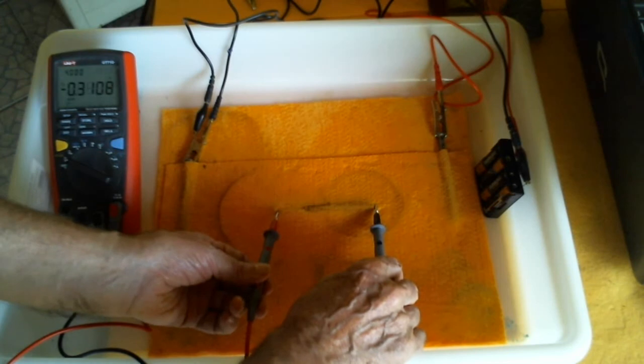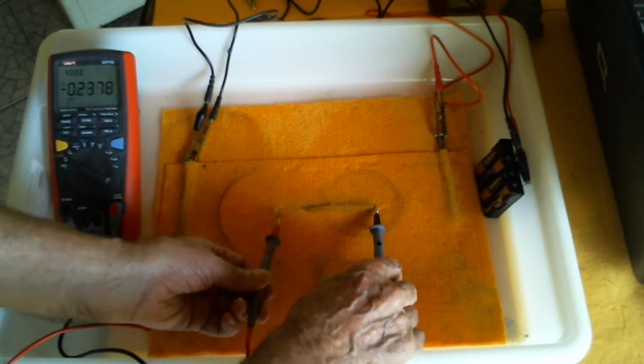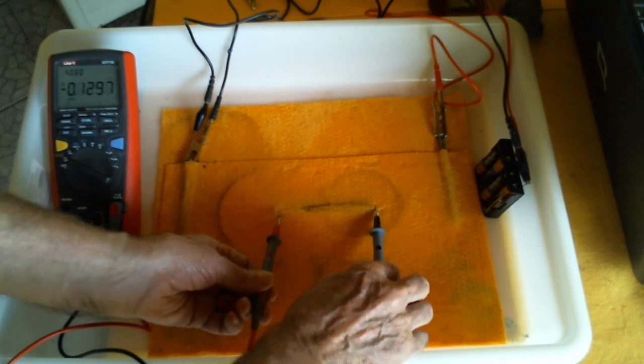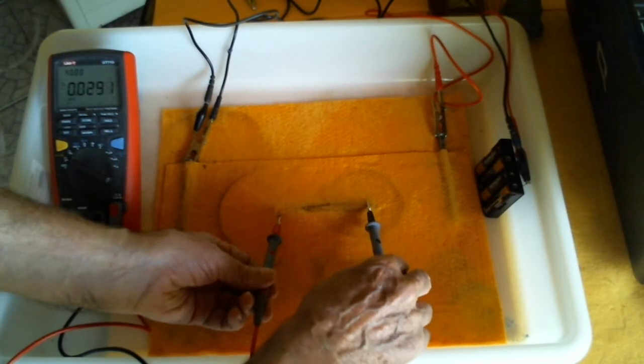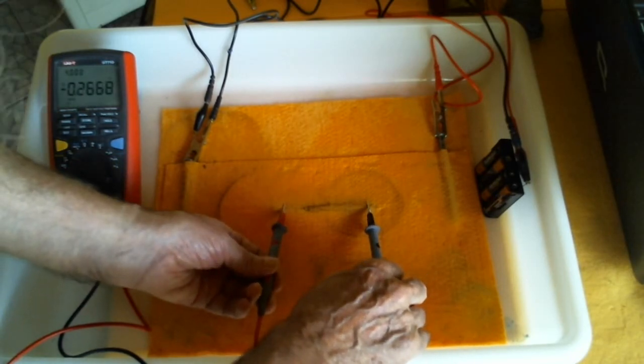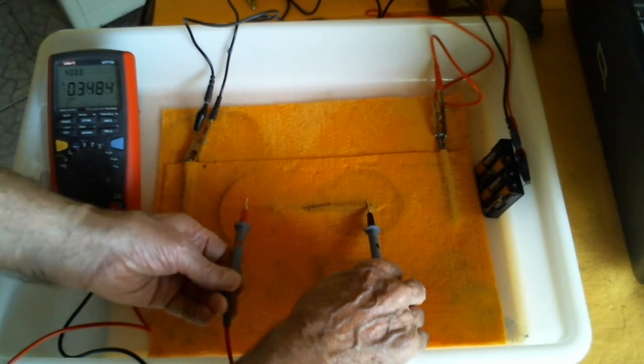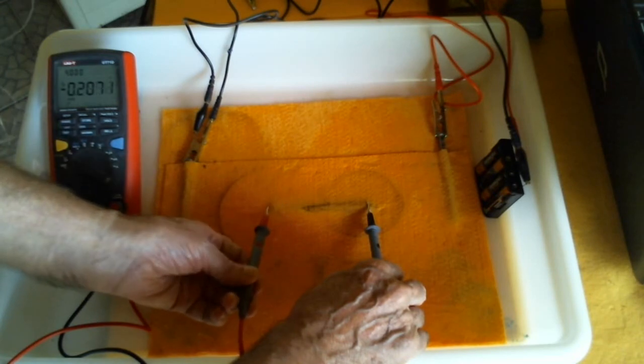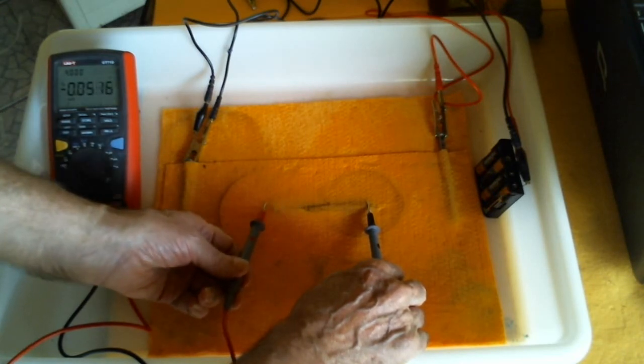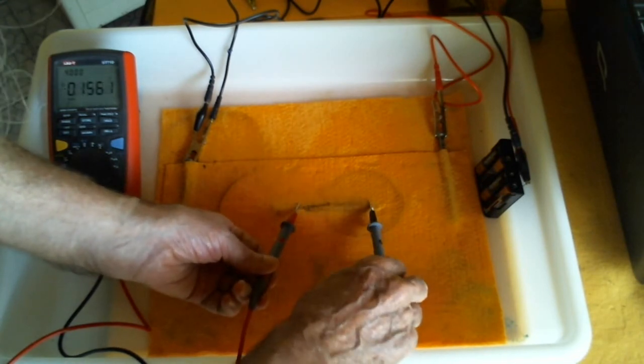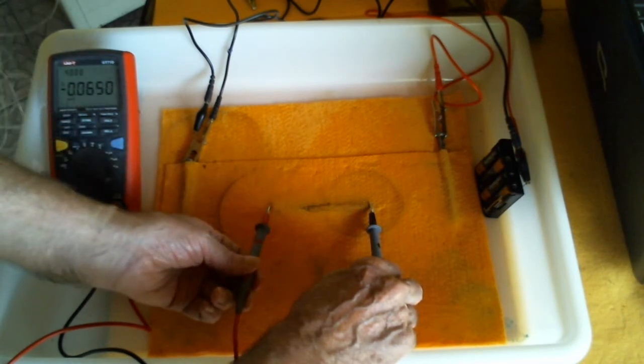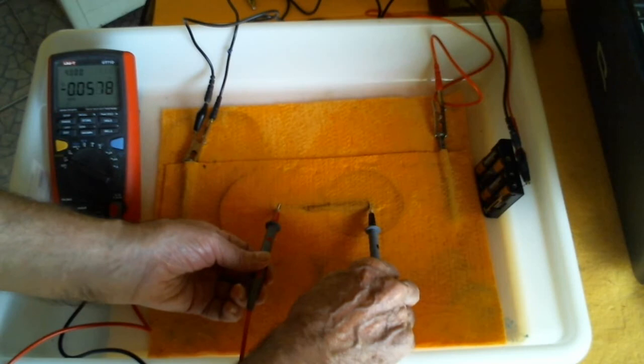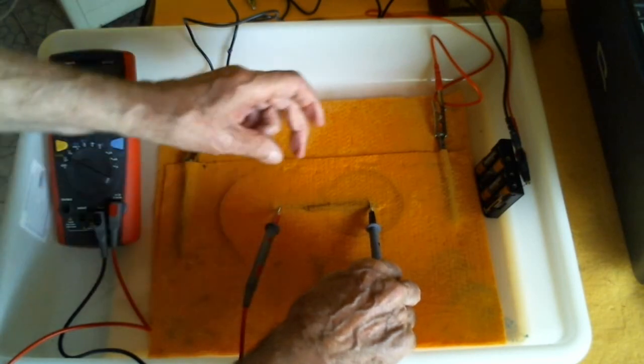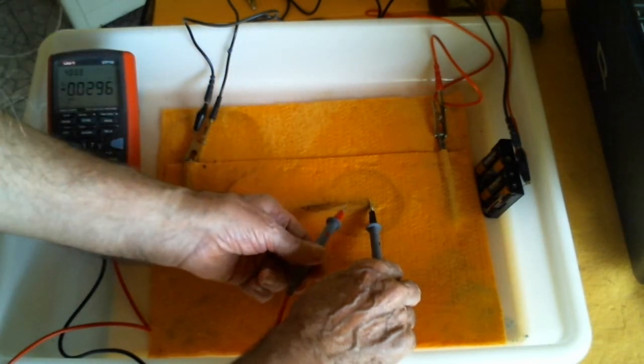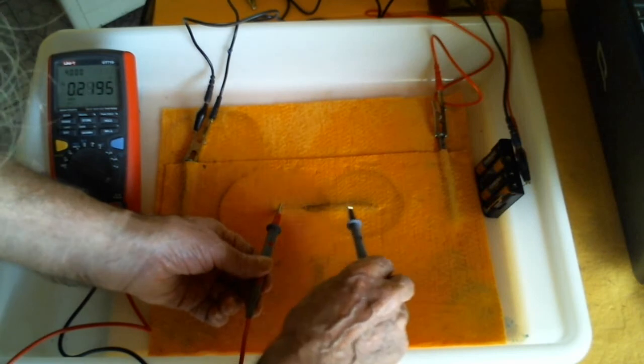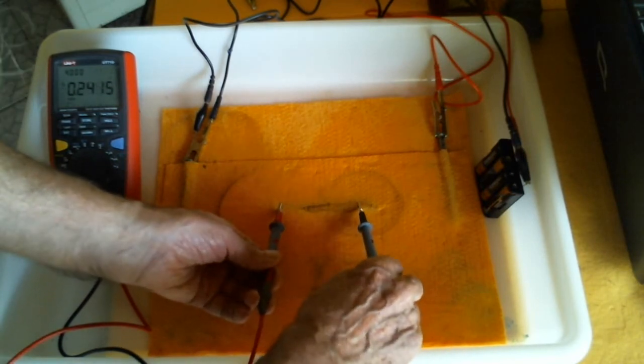Now, where charges leave the electrolyte, the metal, sorry, they carry with it metal which is dissolved. That is what Faraday said. Faraday was right. So we would expect now, according to Faraday, to see the metal of the nail here is protected, it's not corroded, and the metal here to be corroded. And we can actually tell the potential of the metal in relation to the electrolyte. So we are getting a discharge in this area, and we can measure the discharge on this